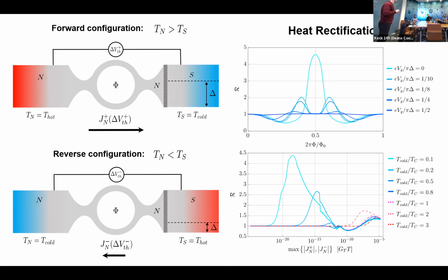Another important feature that I want to describe here is the relation between rectification and the actual value of the heat current. Because in general, the better the rectification, the smaller the heat current that you're rectifying. Here I represented in a parametric plot the rectification factor on the vertical axis versus the value of the heat current on the horizontal one. You can see that the best rectification corresponds to very, very low values of the heat current.